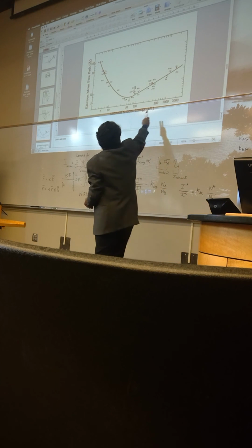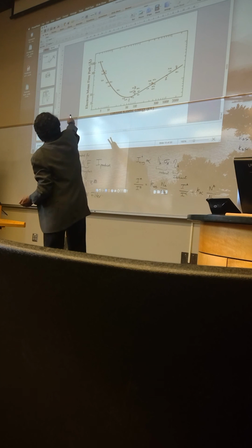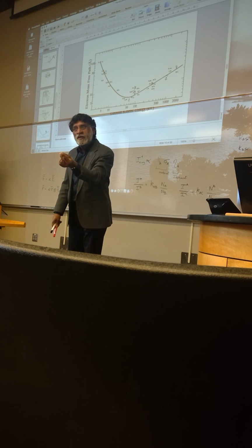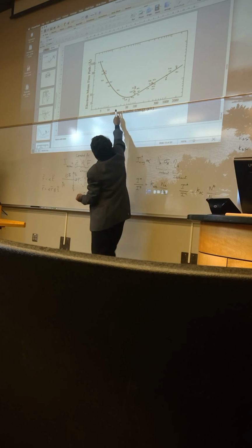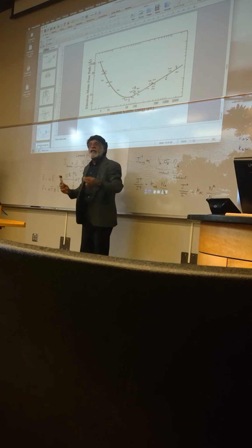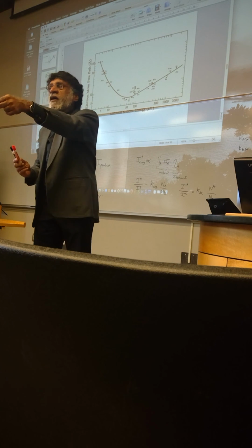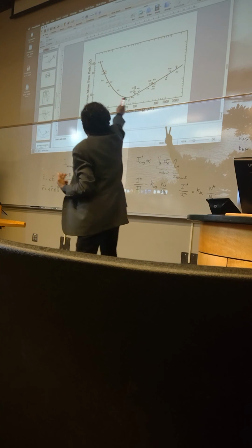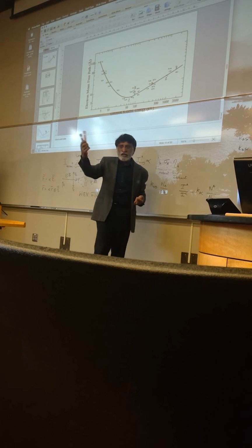Over all the way up to 2 keV, for all the elements, the maximum distance it can travel is 1,000 angstroms. For most, 100 angstroms. And for most of the elements, it travels between 5 and 10 angstroms before it hits some other electron and loses energy. This is why this is surface. We'll take it from here in the next one.